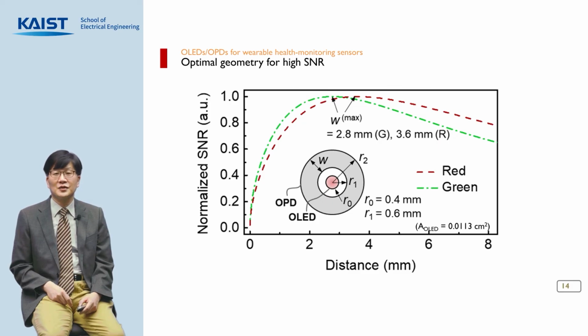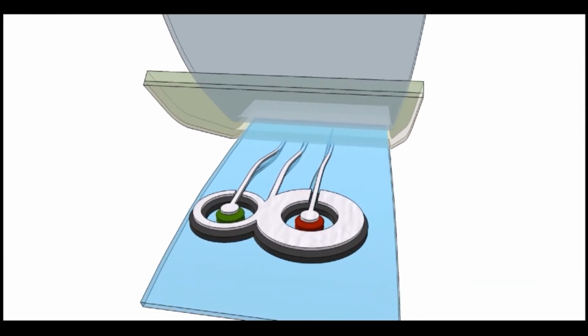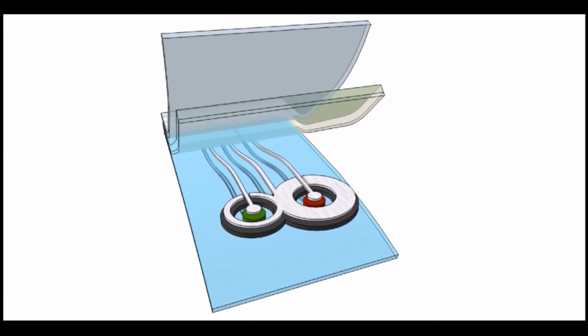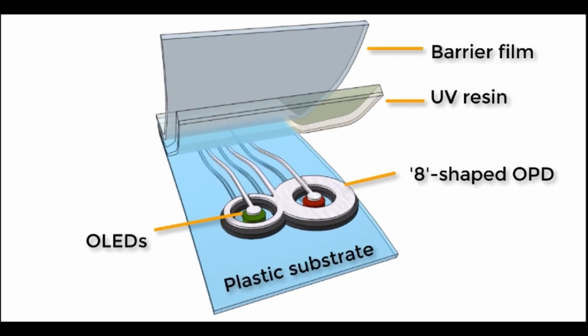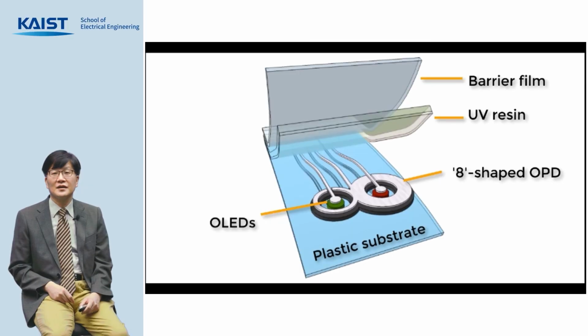Considering the fact that the photodiode noise continues to grow with the square root of the detector area, and that the signal gets saturated at some point due to the finite lateral propagation length of the light, we were able to identify the optimal dimension of a concentric geometry where organic photodiodes wrap around a circular OLED. We then utilized the easy patterning capability of organic technology to realize an ideal design that can make smarter use of photons than the conventional linear arrangement of LED and photodiode.